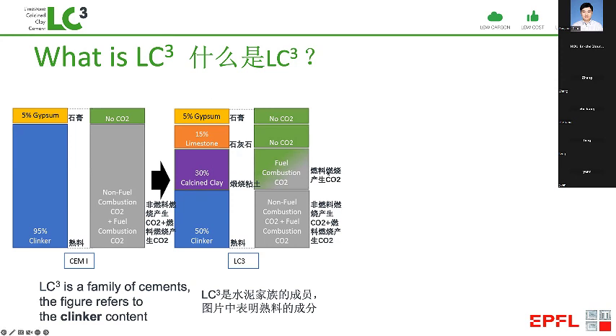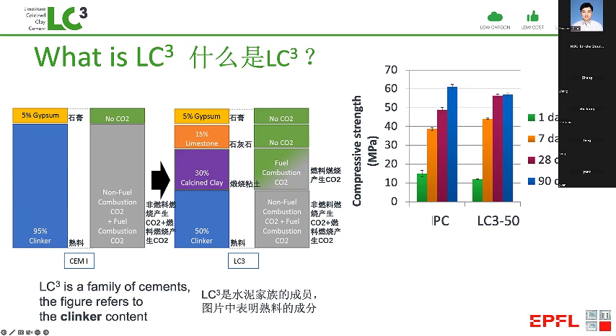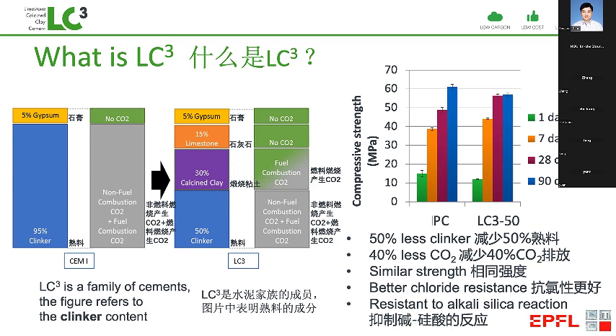However, even at this level of substitution of 50%, we can have materials which can exceed the strength of the reference in only a few days. And this is in very sharp contrast to traditional SCMs like fly ash, where we may have to wait 90 days to recover the same strength as the reference. With LC3, we can do this in 3 to 7 days. So simply put, this is 50% less clinker, 40% or more less CO2 with similar strength and some properties like chloride resistance and resistance to alkali silica reaction are vastly improved.